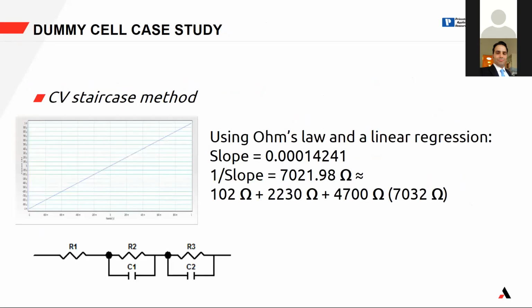If you do a cyclic voltammetry, you receive this signal. It's an interesting line. From this line, using Ohm's law, you can take the linear regression. You take the slope, 1 divided by the slope, and from this value you get the value of the total resistance. So 1 divided by the slope is equal to 7,021.98. If you calculate, we are very close to the sum of the three resistances. But I don't know if it's R1, R2, or R3. I have the total, and I don't know the value of the two capacitors.